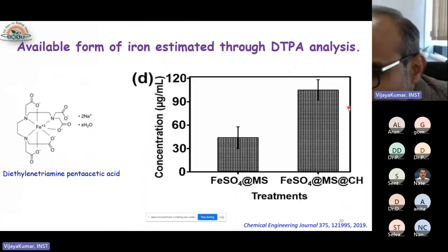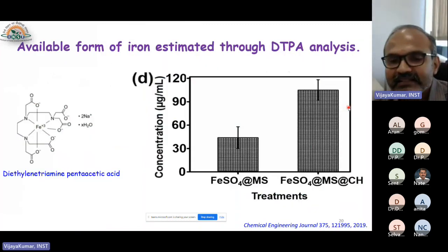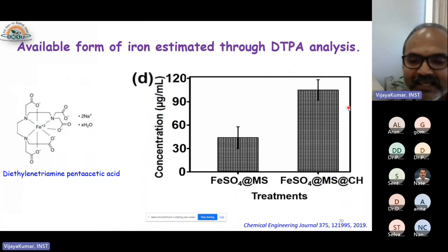And now the next question is whether the designed material is able to be stable and withstand the FeSO4 as such in spite of the carbonate bicarbonate. So we added saturated carbonate bicarbonate solution into the chitosan coated material and kept it overnight, and then we used this DTPA extract. This is a classical soil science method that will show the available iron in the material. Once we extracted, we were able to see a 3 times increase in the available iron when coated material is used.